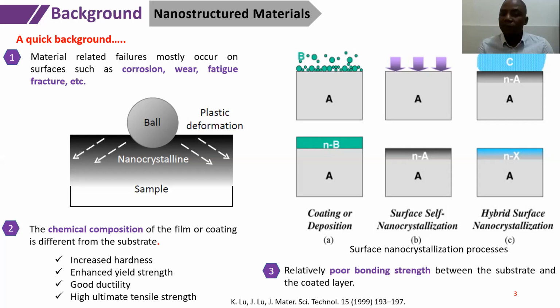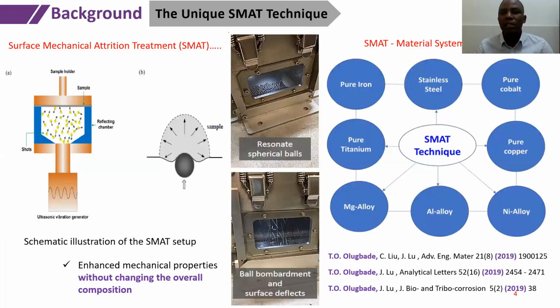Now, we have various forms of this surface treatment. Among these, we have one particular one that is being developed in my group, which we call surface mechanical attrition treatment. This method involves the bombardment of the surface of the material with very fast, high-moving balls. As you can see here, we have the resonant spherical balls. The ball moves at a very, very high speed, hits the surface of the sample, creates a nanograin layer on the surface of the sample, then creates nucleation sites, thereby enhancing the property of the material. One good thing about this method is that it improves the properties of the material without changing the overall composition of the material. The method has been applied to materials in our group, and some of them have been published already and made known to the public.